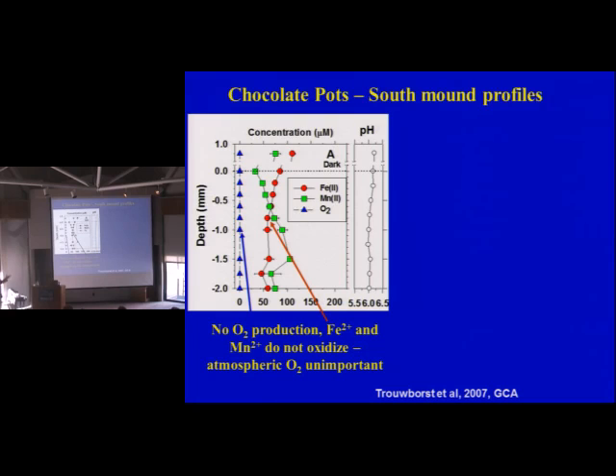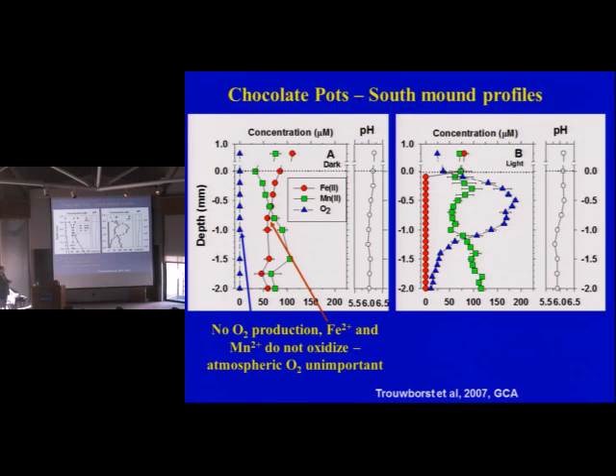So what this means is that with no oxygen production, iron-2 and manganese-2 are not being oxidized. And notice that atmospheric oxygen is unimportant. The flux of oxygen across an air-water interface is really slow, so we're not seeing any effect from that. Now, if we go to a light system, all of a sudden you see that we're getting a peak at about 0.5 millimeters. This scales in millimeters on the y-axis. And we're right at the saturation point, and a little bit higher than saturation because it's 55-degree water. This is flowing water, by the way. So now we have oxygen titrated to the point where it's a maximum. It takes out all the iron. But notice you can measure iron above the air-water interface. There is some efflux of oxygen from the production of oxygen by the cyanobacteria to the air-water interface, but it's not taking out all the iron. Notice that the manganese is still there. It's not being taken out.